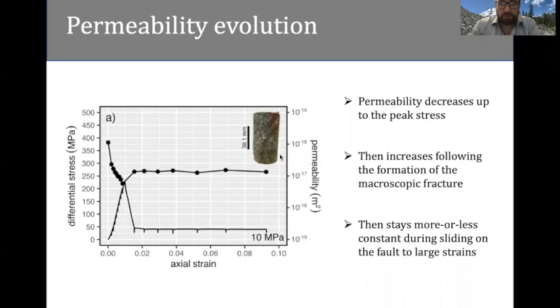So it decreases from a permeability of 10 to the minus 16 down to a permeability of about 10 to the minus 17. Upon the formation of the macroscopic shear fracture, which is also shown in this small inset here, we see that there's an increase in the permeability of the sample.